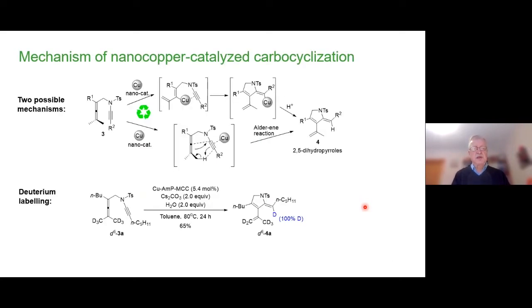Now to the mechanism on this nanocopper catalyzed carbocyclization. We have considered 2 mechanisms. The upper is following the same pattern as the palladium, where we have a CH activation and form a vinyl copper and cyclization. But look here, you have only to look at this vinyl copper. This is crucial for the mechanism. Now, if it's hydrolyzed, you will get this proton in this position. However, if you have the lower mechanism, which is an ene reaction, this hydrogen that ends up here in the vinyl comes actually from the molecule in an intramolecular reaction.